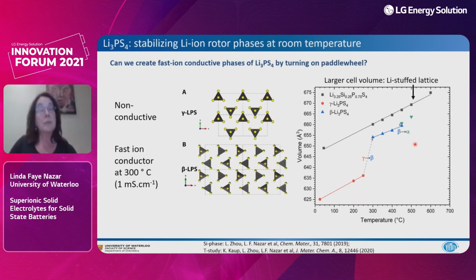So after we did that work, we then decided to extend it to some lithium-ion conductors, and that's what I'll be talking about in the next few slides. And so the question that we asked ourselves was, can we create a fast ion conductive phase of boring old Li3PS4 by turning on paddle wheel effectively at room temperature? So LPS, as we call it, is in the gamma phase. The room temperature phase is completely non-conductive. It's an extremely poor ion conductor. But at 300 degrees centigrade, it becomes a reasonably good fast ion conductor, about 1 millisiemens per centimeter. And it undergoes a transition to the beta phase.